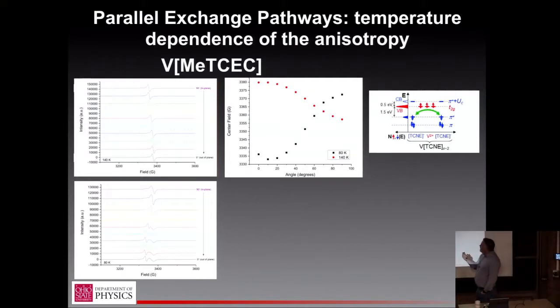And so what this means is that the easy axis changes as a function of temperature of measurement in these films. Same film, exact same sample. So basically the easy axis has gone from in plane to out of plane. And so this is one of the pieces of data I was referring to that makes us think that maybe there's more structural order than we thought. And I think to explain this, I need to jump back to another slide that I skipped over.